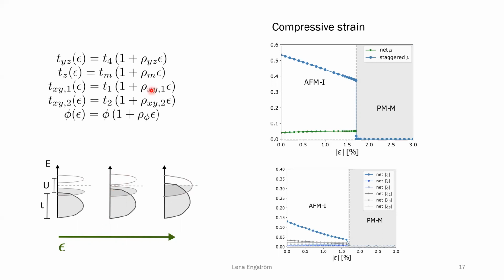Since we have different hopping parameters for the different orbitals, it will mean that not only do we broaden these 2 types of bands, but we actually bring the J1/2 bands and the J3/2 bands closer to each other. So at some point, we actually get a Fermi surface with these J1/2 bands, and they become much more relevant for the state that we are considering.